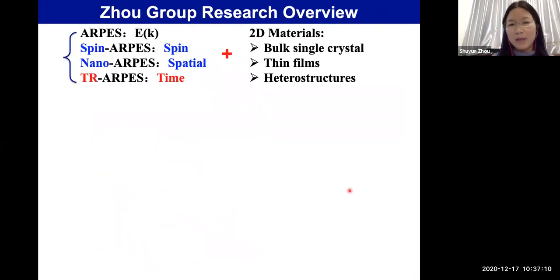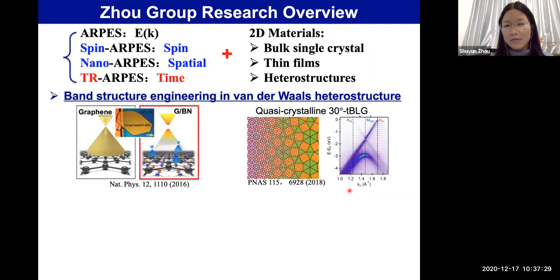Using a combination of ARPES, spin-ARPES, nano-ARPES, and time-resolved ARPES, we are interested in revealing the band structure of 2D materials, ranging from single crystals and thin films to heterostructures. A few examples of research work done in my group in the past few years include the band structure engineering of graphene-boron nitride heterostructures, these are secondary Dirac cones. And also we reported the electronic structure of this 30-degree twisted quasicrystalline bilayer graphene.